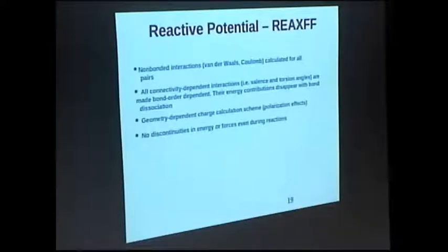No discontinuities in energy. And here is one of the biggest things that is also a feature that is valid for COMB potentials. We have only one parameterization for each element. Then we don't have many carbons, sp2 or sp3 or sp carbon. We have only one carbon in each parameterization.